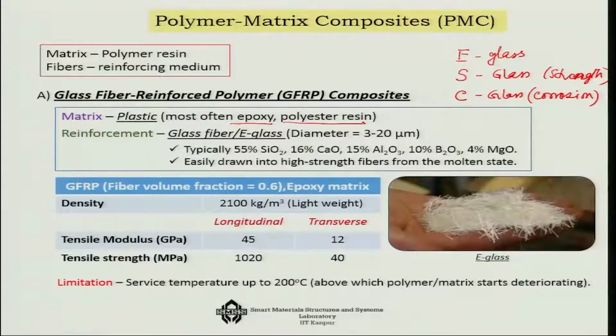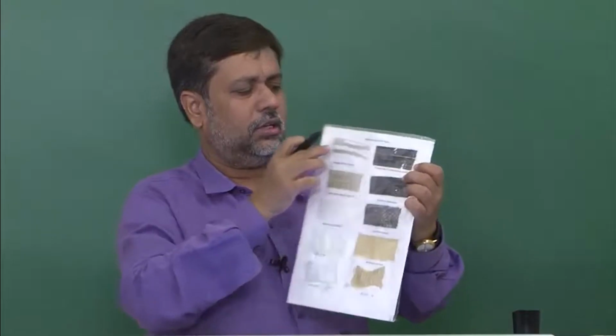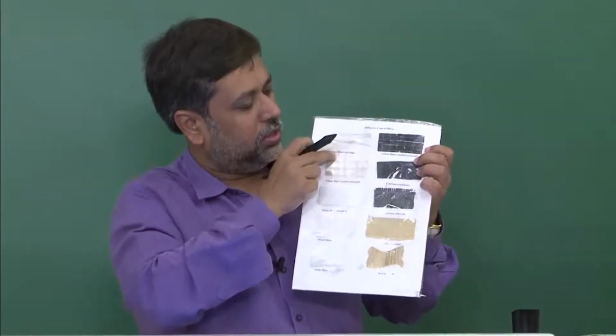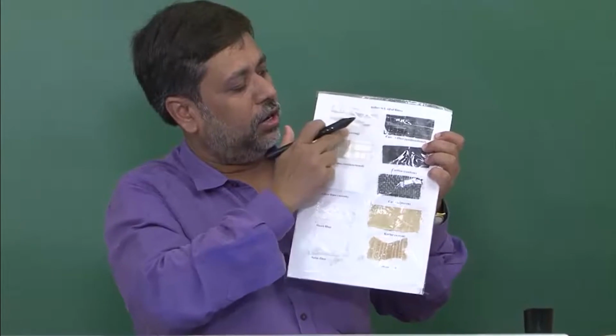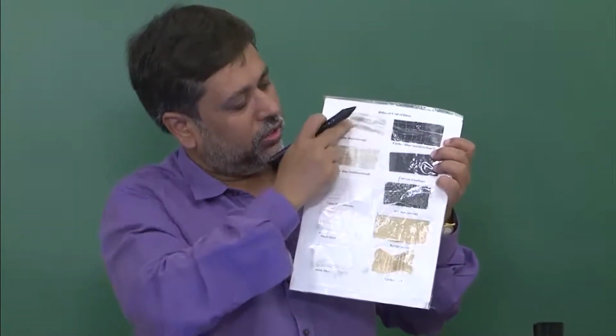The diameter of this fiber is between 3 to 20 micrometer. And typically in each one of these fibers, if you look at the composition, you will see about 55% silica. So silica has the major composition, then 16% calcium oxide, 15% alumina, 10% boron oxide, and 4% magnesium oxide. All these things together make the glass fiber. In fact, you can see the glass fiber here. The first one and the second one are the two where the fibers are whitish, transparent or translucent in nature. These are the glass fibers.